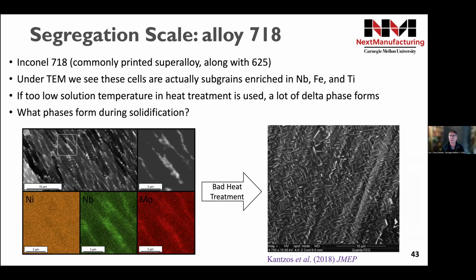Well, we're interested in, for example, nickel alloy 718. This is an alloy that has been around for several decades. The reason that we print with it is, along with 625, it's one of the few nickel alloys that was known to be printable from the beginning, and that was based on its weldability. So you see a connection to sort of old line metallurgy, if you like.